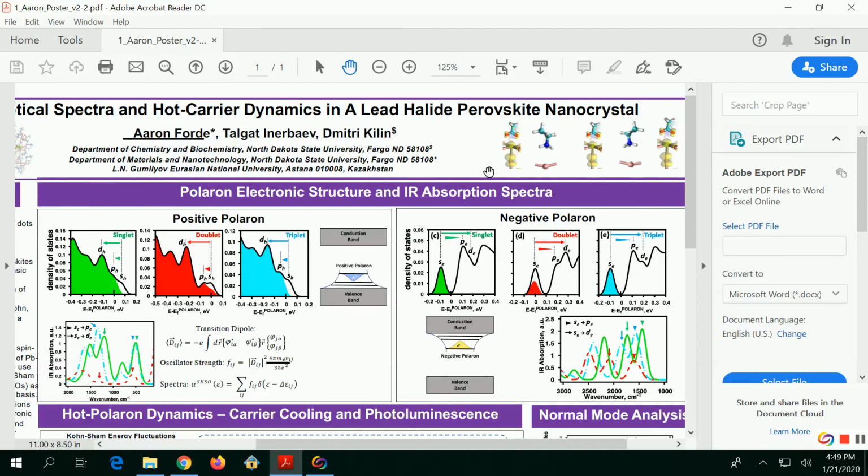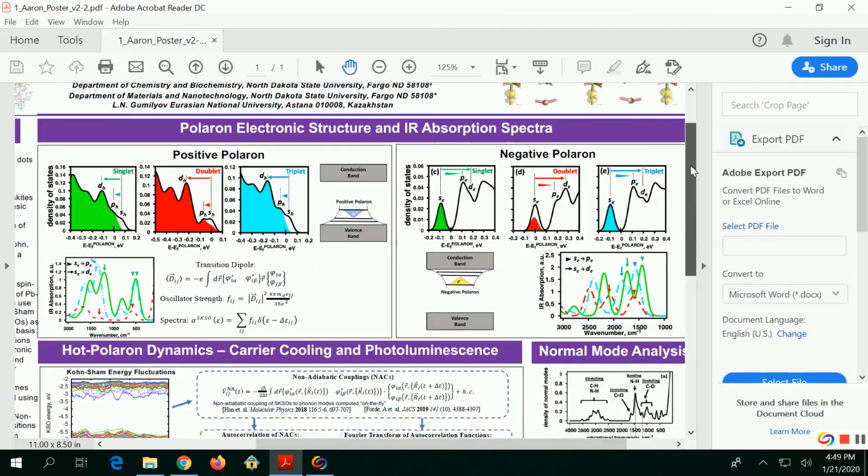If you consider the surface of the perovskites, these are carboxylates, which form chemical bonds. That's illustrated with the electron density, whereas the ammoniums coordinate to the surface, but they don't directly bond. So they wouldn't provide vibrational modes to couple.